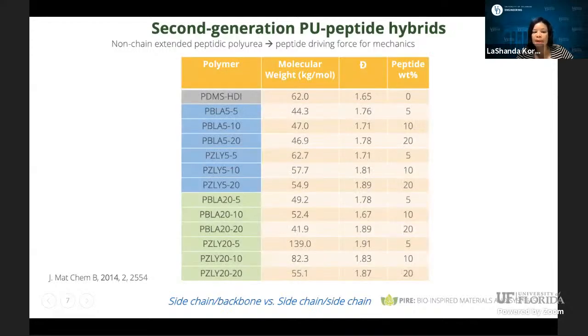So we wanted to look at, are we able to use this mechanism and still build up sufficient molecular weight to be above the entanglement molecular weight? Again, thinking about how we can form films and potentially fibers from this system. So you can see that these are all well above the 35 kilograms per mole in these systems, with dispersities that are consistent with that of a step growth polymerization.